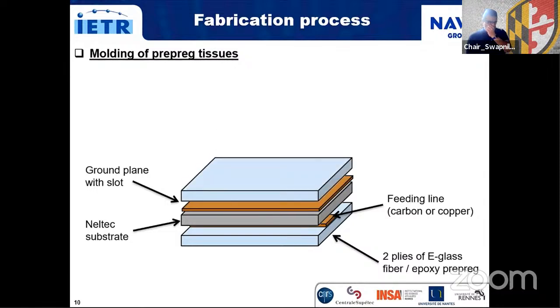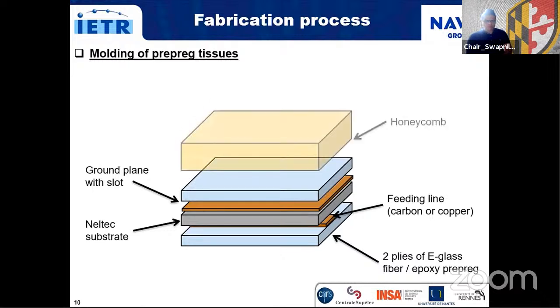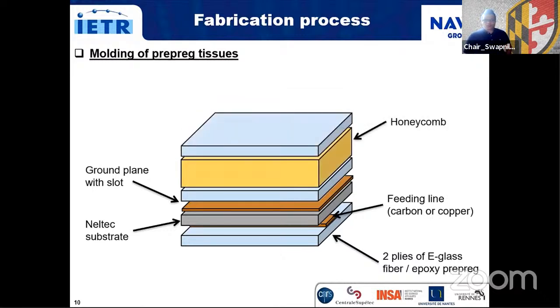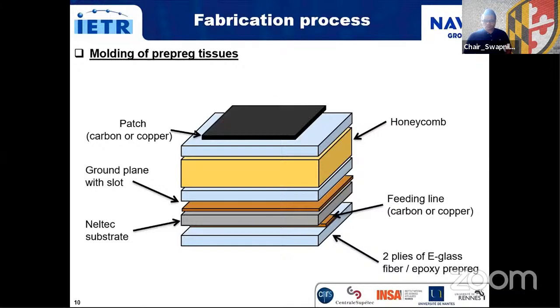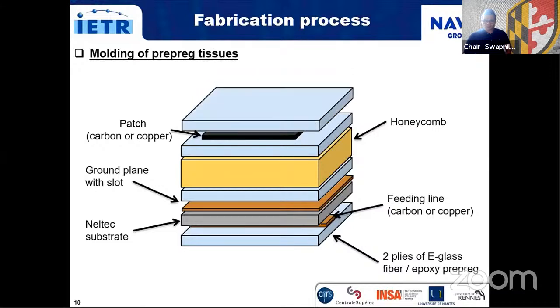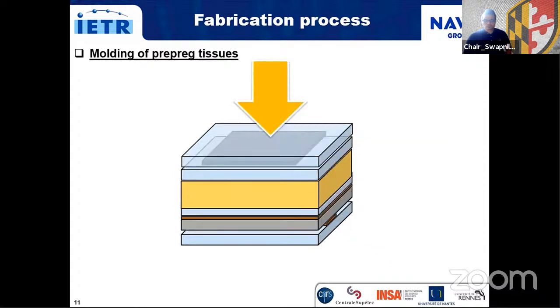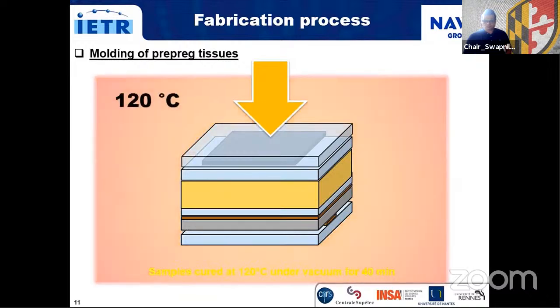Then, two plies of e-glass fiber epoxy prepreg, the honeycomb, two other plies of e-glass fiber epoxy prepreg, the radiating patch in carbon fiber tissue or copper sheet cut to the required size, and at last, two plies of e-glass fiber epoxy prepreg for radome. Both samples are compacted under vacuum with a plastic bag and cured at 120 degrees for 40 minutes.